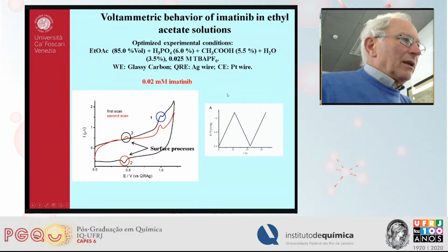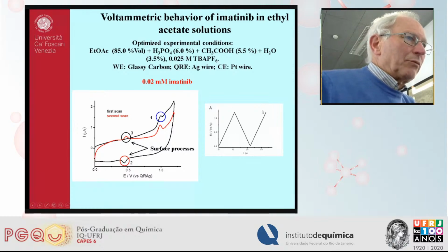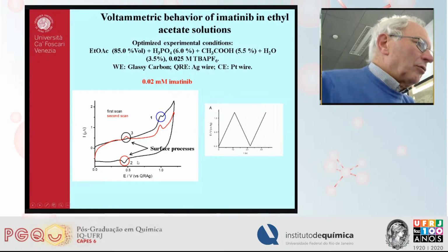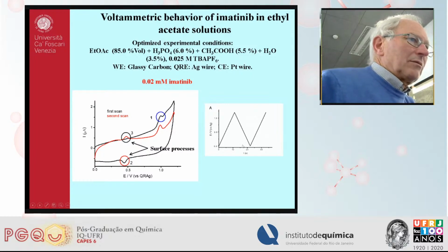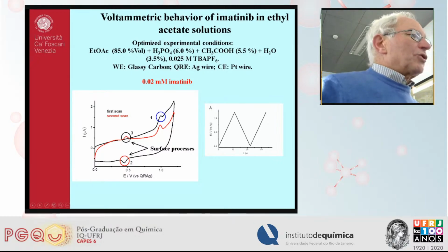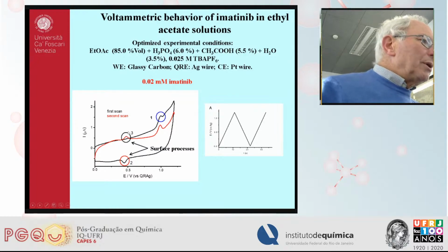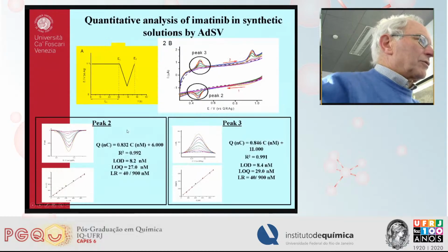In this case, we used for the investigation this waveform, which is cyclic voltammetry with 3 segments. In the first stage, in the anodic region, we got this peak here, which provides products which adsorb on the electrode surface. So this is the forward scan. When we go back, there is this peak here, and going back again with this segment, we got this peak here. So these 2 peaks are species which are adsorbed on the electrode surface, and they provide a good way to detect this drug at low concentration levels.